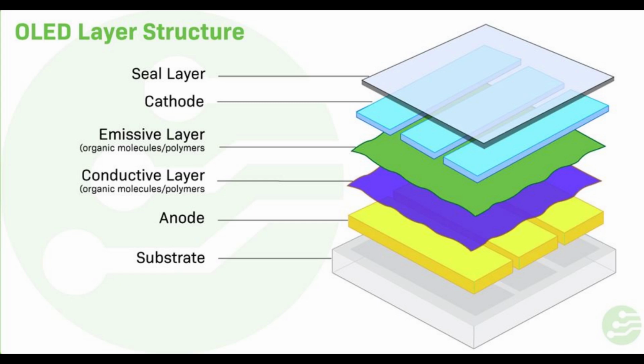An alternative configuration is to switch the mode of emission. A reflective anode, and a transparent, or more often semi-transparent, cathode are used so that the light emits from the cathode side, and this configuration is called top emission OLED, TEOLED. Unlike BEOLEDs where the anode is made of transparent conductive ITO, this time the cathode needs to be transparent, and the ITO material is not an ideal choice for the cathode because of a damage issue due to the sputtering process. Thus, a thin metal film such as pure Ag and the MgAg alloy are used for the semi-transparent cathode due to their high transmittance and high conductivity.